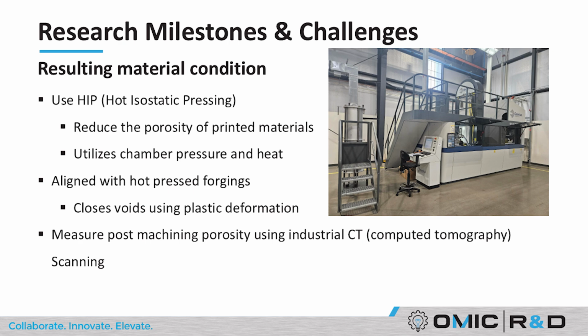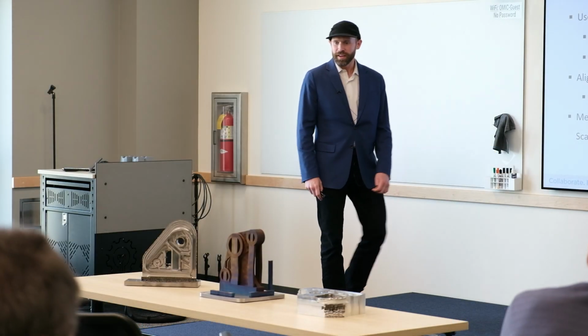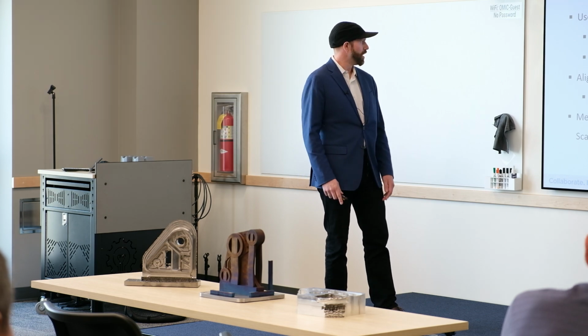So we use the HIP. Quintus has been a very good partner with Trent to produce heat treatment cycles for all of these parts. We're able to run a lot of porosity out of these parts. I know laser powder bed fusion already doesn't have too much porosity in it, but wire arc additive does, and it's very prevalent in this piece specifically. The other ones I have out at a CT scanning company now, so I wasn't able to have one here that was hipped.